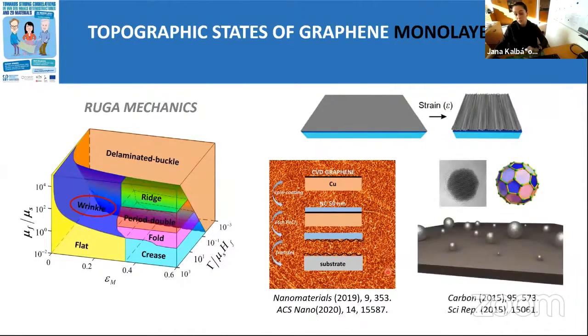So there is another possibility for how to do it, and this is quite simple and straightforward. Instead of using polymers and tuning the mismatch strains of the substrate and the graphene, we can simply use a decorated substrate. So you use a substrate, you deposit your sources of corrugation, which could be particles, could be fullerenes, could be anything you can imagine. On top of the decorated substrate we transfer the graphene, and as a result we can control the amount of corrugations on the surface. This is quite powerful, and it has been demonstrated that for graphene monolayers it works quite nicely. Nevertheless, I have seen that graphene bilayers nowadays are a highlight.